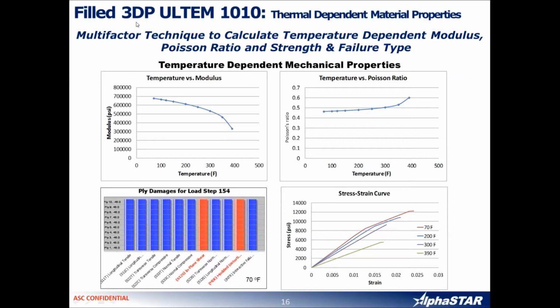For example, for a 3DP ULTEM 1010, as you can see, we use a multi-factor technique to calculate the temperature-dependent modulus, Poisson's ratio, and strength and failure type. On the upper left, you see the temperature versus modulus. Then on the right side, you see the temperature versus Poisson's ratio, and on the bottom right, you see the stress strain curve generated using this multi-factor technique for different temperatures, for 70 degree, 200, 300, and 390 degree Fahrenheit.